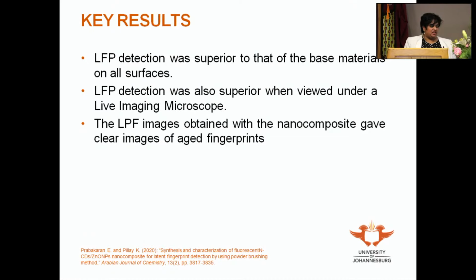And something else that was useful is that this nanocomposite material was able to give us clear fingerprint images of aged fingerprints. Now that's important because sometimes crimes get reported after some days or months and you really need proper evidence. So if you can develop a material that can do that, it will really achieve great results. And that wasn't the only forensic application that we engaged in.